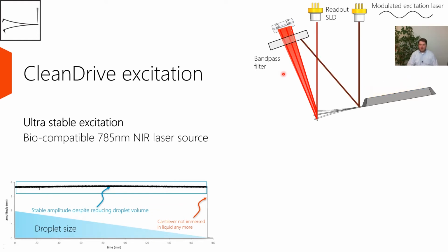With clean drive, what we do is we use a second light source that we focus to the base of the cantilever, and we modulate this light source in intensity. Actually, we're using a 785 nanometer NIR laser source, which allows us to also be compatible with optical microscopy and biological samples. By modulating the intensity here, we locally heat the cantilever at its base, and this way we start exciting the cantilever. But we just excite the cantilever, not the whole chip, not the whole scanner or the whole cantilever holder. It's just the cantilever itself which is excited. And this way the coupling to the environment is much less.